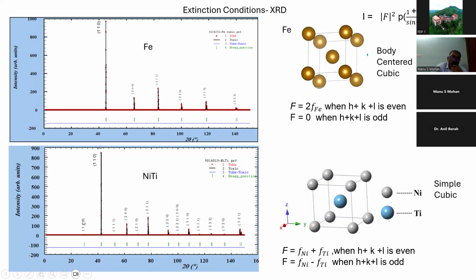So you get all the peaks. You will see 100 here - 1 plus 0 plus 0 is 1, again it is odd. Similarly 210 is odd. So not only for even reflections, but for odd also you see peaks. So that is the difference.